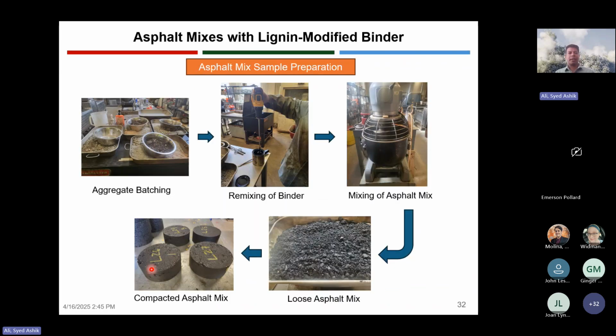Okay, here is the asphalt mix with the lignin modifiers. This is the process we used. We batched the aggregate, and although the asphalt binder was already mixed with the lignin, before putting this asphalt binder in our aggregate, we wanted to make sure the lignin is suspended properly and uniformly distributed. So we mixed for 2-3 minutes using, as you can see, a drill here. We made sure that the lignin is suspended in the asphalt binder, and after that we used this agitated, modified asphalt binder in producing the asphalt mix, and this is the loose mix as you can see. Then we compacted the asphalt mix and used it for rutting, cracking, and moisture-induced damage evaluation.